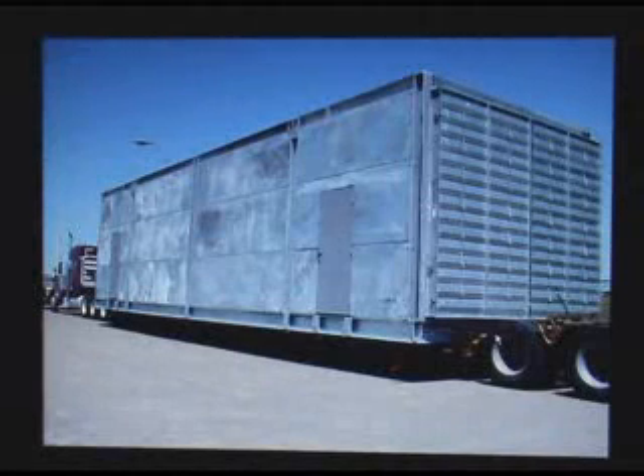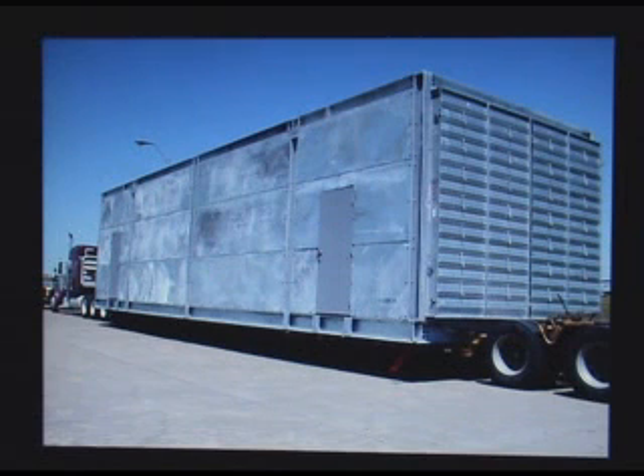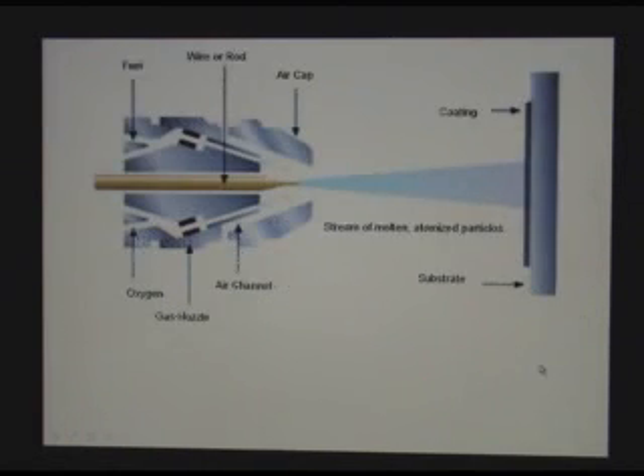Here is a bigger structure, completely hot dip galvanized. I think this is an air cooler enclosure we used at the North Slope. Then another method to apply metal to carbon steel surfaces is metal spraying. In the past we used aluminum and zinc, and this process is very simple. Wire rod is melted in a gun, and then the molten metal is propelled with air onto the surface, which was prepared before to accept this metallic coating.